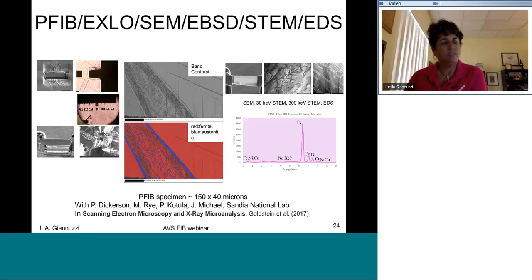People would always ask me, can you make a TEM sample? You know, this was a few years ago. Can you make a TEM sample with plasma FIB? And the resolution, the first numbers that were being thrown out there were sub 50 nanometers. I'm going to show you examples when we talk about TEM sample prep. The initial techniques were developed in the mid to late 90s using a glass column gallium liquid metal ion source FIB with a resolution of 50 nanometers. The plasma FIB came out and it was already better than that. So of course you're going to be able to make TEM samples using the plasma FIB.